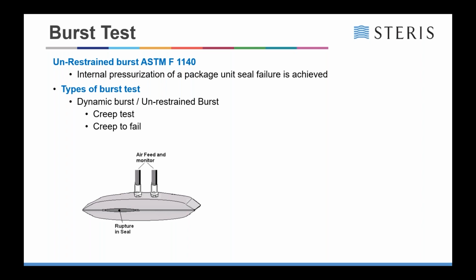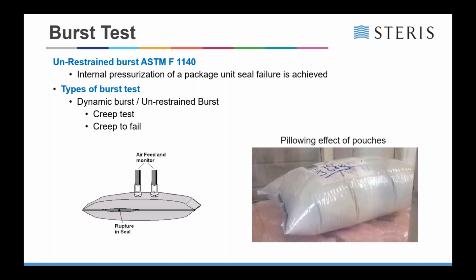So you have the unrestrained burst or dynamic burst, or you have a creep test or a creep to fail test. The big problem with this type of test is the effect of what's called pillowing. When you blow up a pouch, it creates strain on particular areas of the pouch. Those areas may not be the actual weakest point of the pouch, but they will more than likely burst in those areas. So you need to be very careful on how you're doing that.